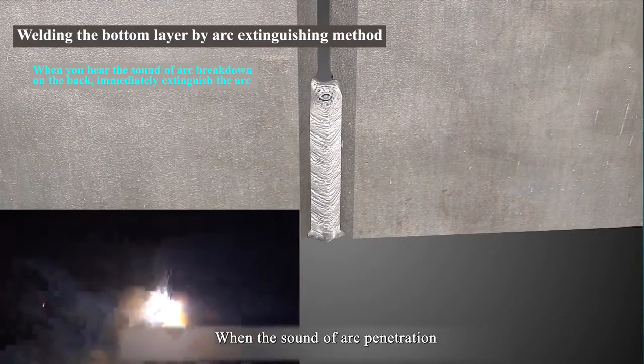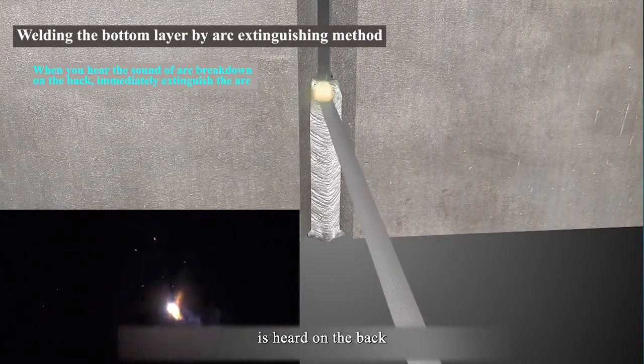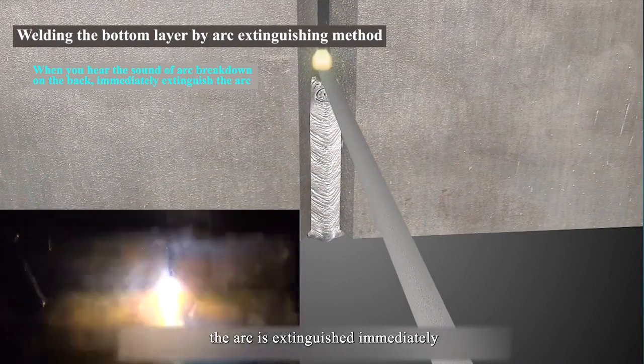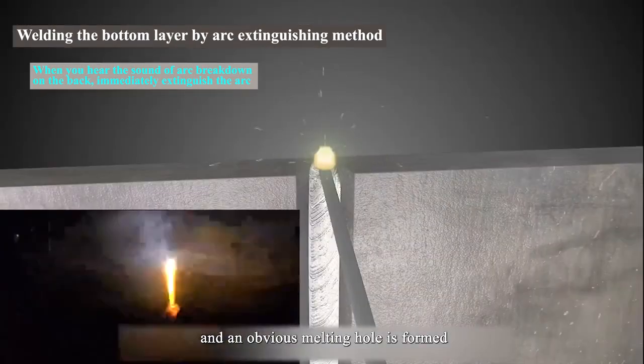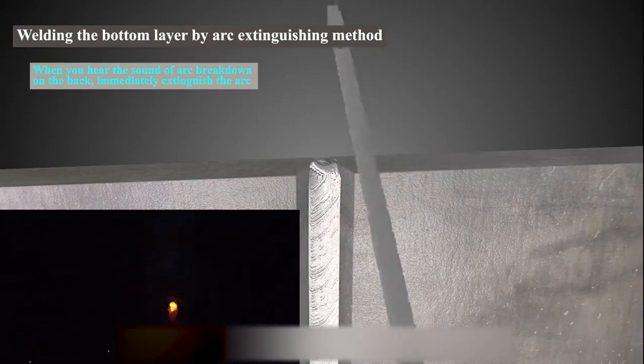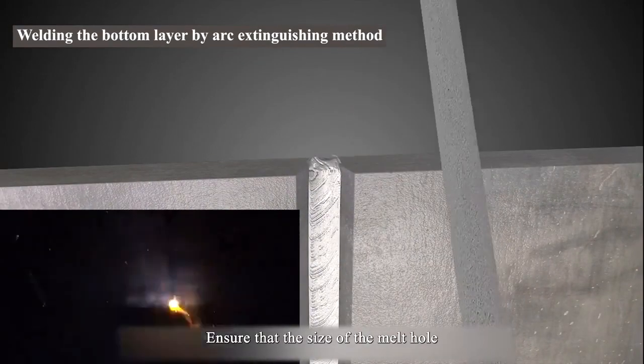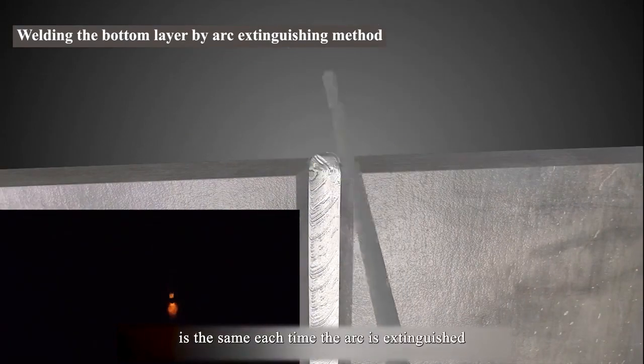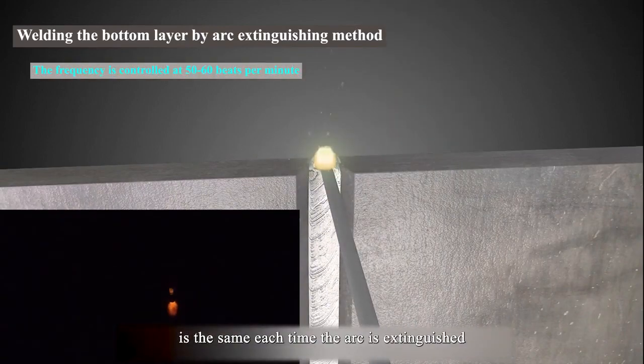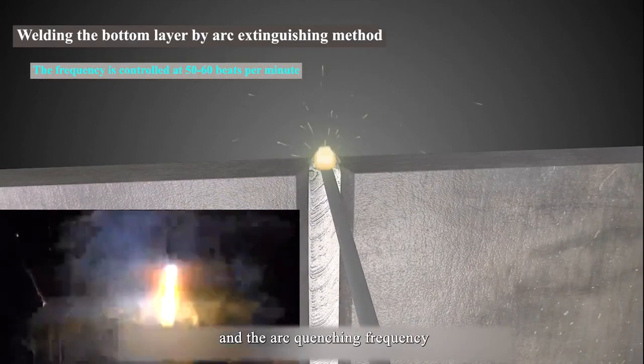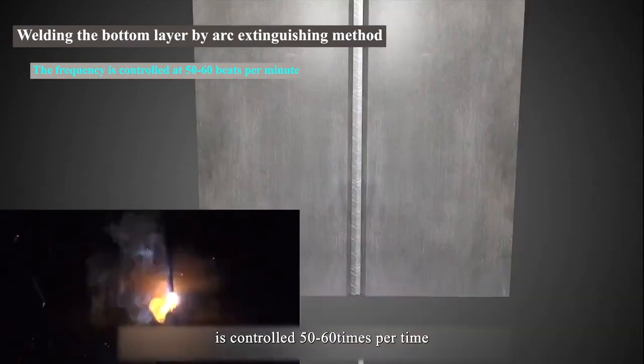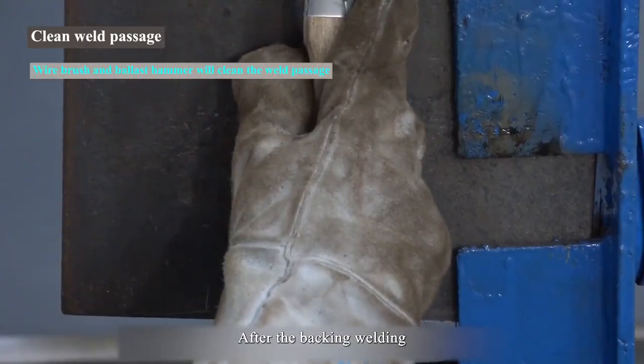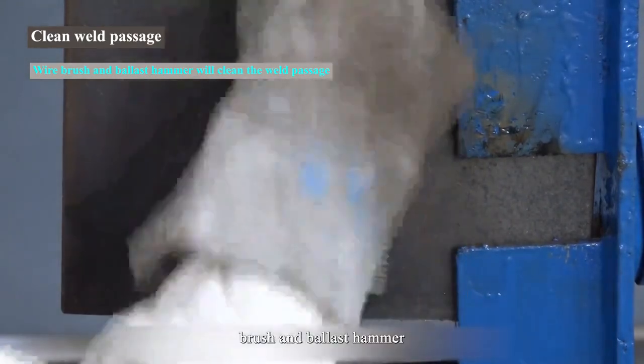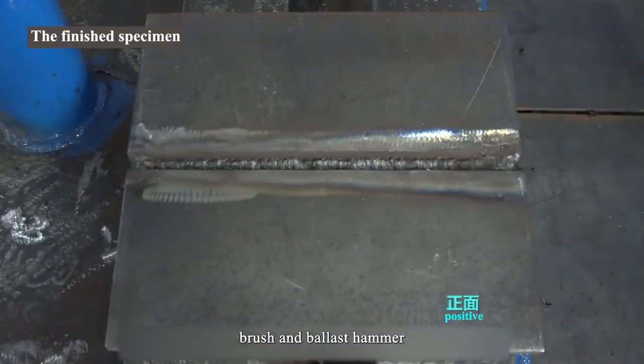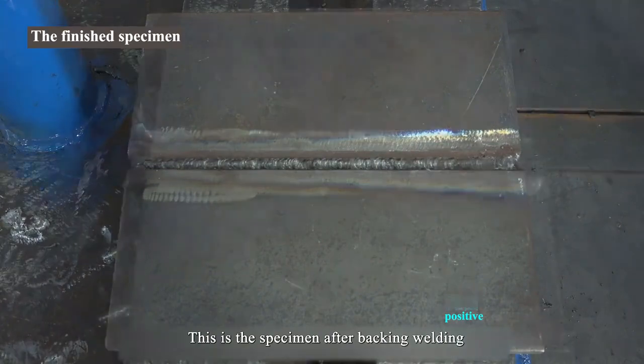When the sound of arc penetration is heard on the back, the arc is extinguished immediately, and an obvious melting hole is formed. Ensure that the size of the melt hole is the same each time the arc is extinguished, and the arc quenching frequency is controlled at 50 to 60 beats per minute. After the backing welding, clean up the weld with a steel wire brush and ballast hammer. This is the specimen after backing welding.